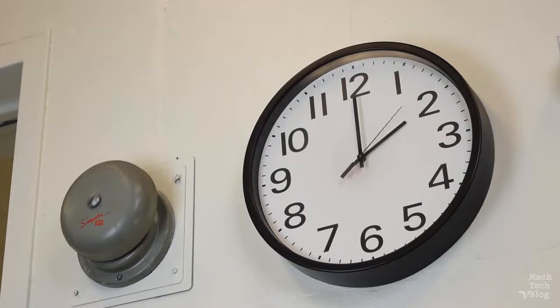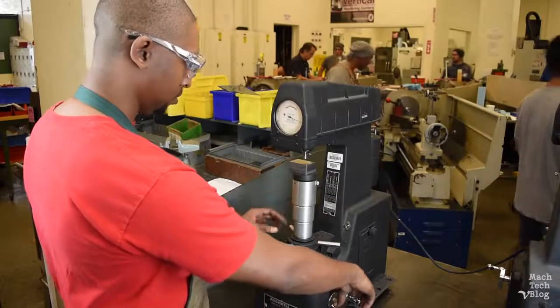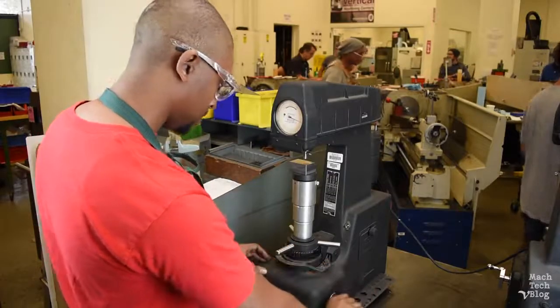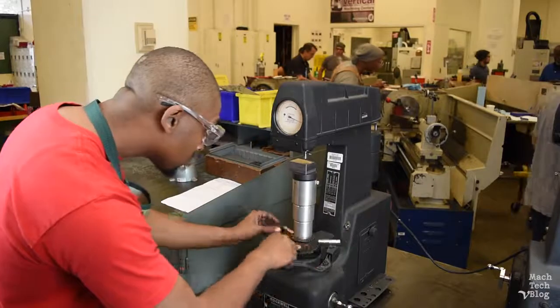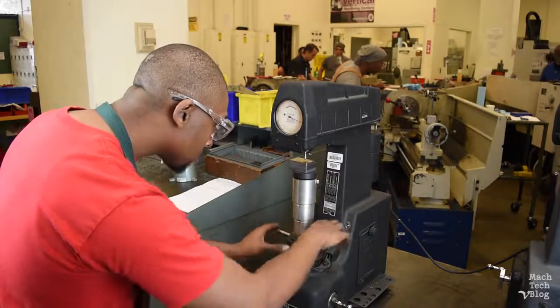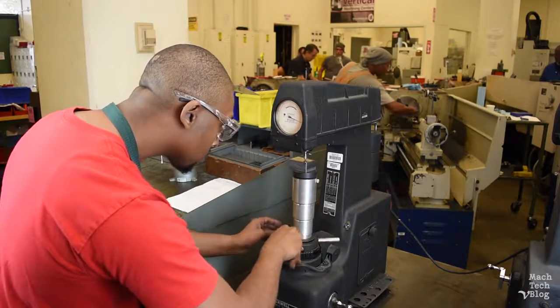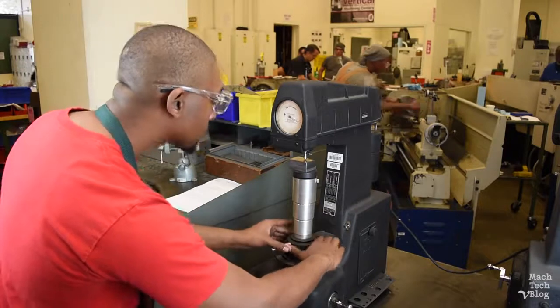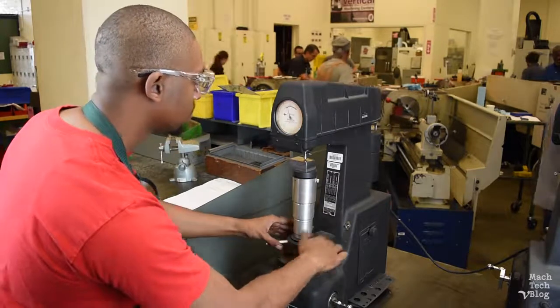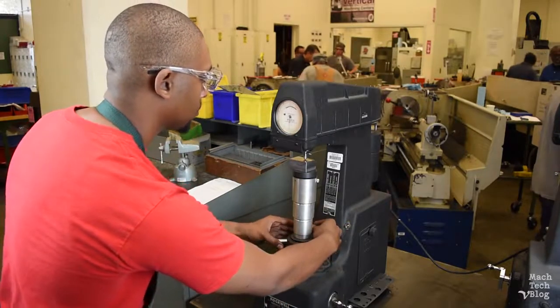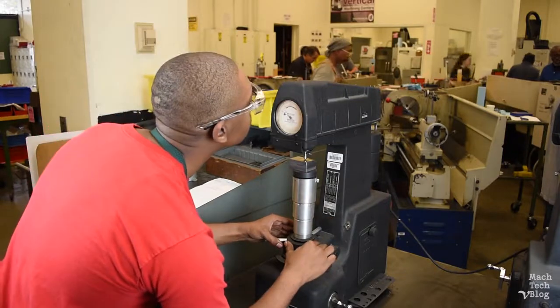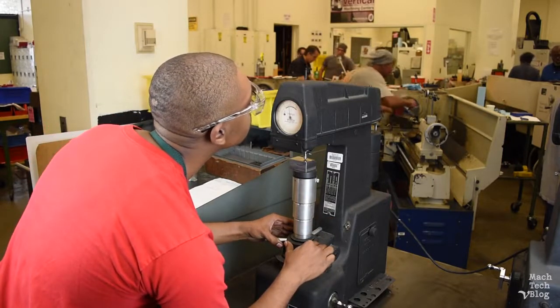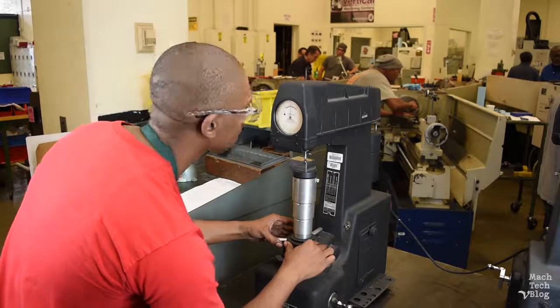Since we've got some time to kill, let's measure the hardness of a piece of untreated 1018 steel using a Rockwell hardness tester. The test is simple. An indentation is made in the material using a diamond tip and a calibrated force. The size of the indentation determines the material's hardness.